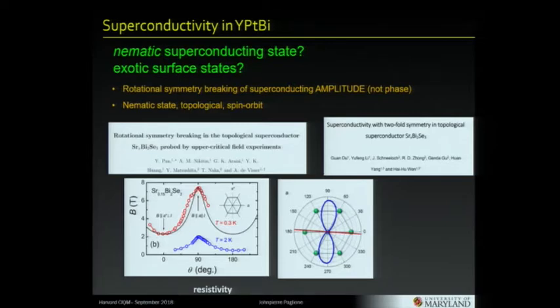Coherence length was measured by the HC2, yeah. And I'm going to show you there's some complication to that as well that I'll show you in a second. So to study that and also to ask a further question, which is based on this really beautiful work on bismuth selenide by a few different groups, showing that there's some anisotropy in the superconducting state that's breaking the crystal symmetry. And it's been called evidence of a so-called nematic superconducting state. So for instance, in bismuth selenide with strontium, you see this nice twofold anisotropy that breaks the hexagonal symmetry. And that's very interesting because nothing else is breaking that symmetry in the crystal.